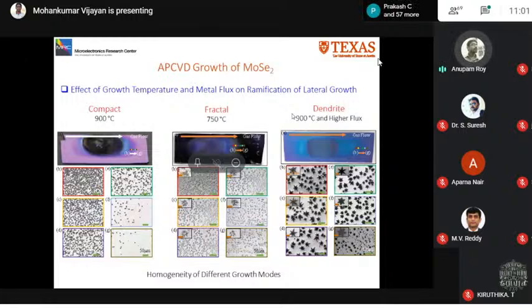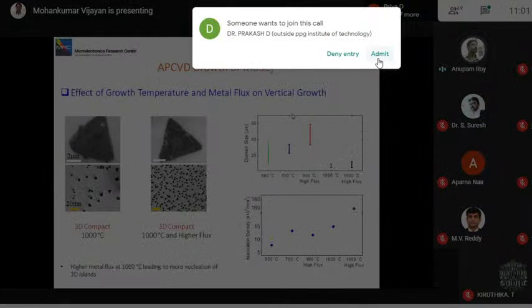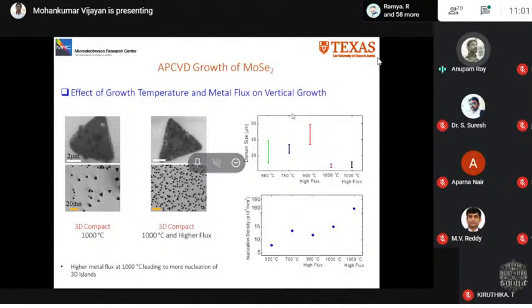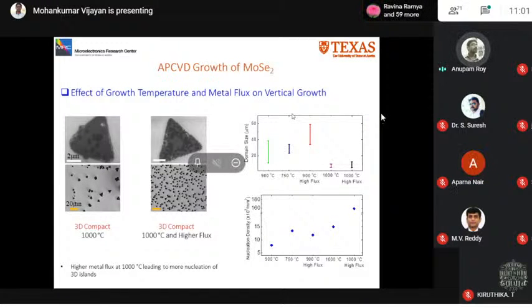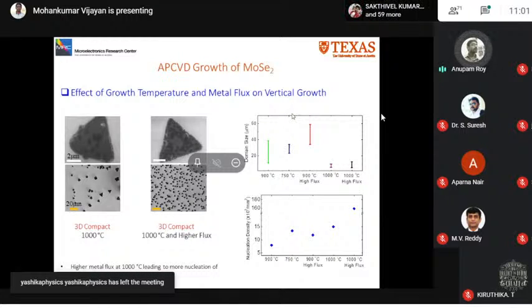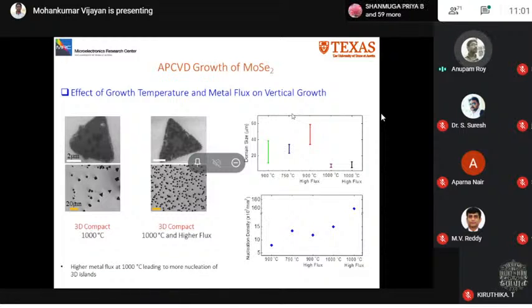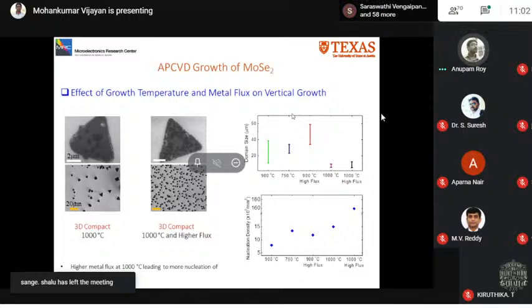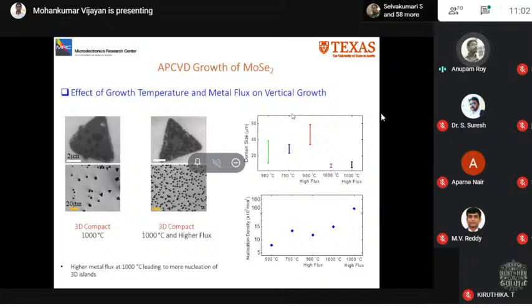In the next slide, I show that when the growth is conducted at a higher temperature, 1000 degrees C, we see that 3D island nucleation appears on a 2D domain, and the island nucleation is more when we have used the higher flux. That is probably because of twofold reasons. One is that at higher temperature we are increasing the metal flux also, and second is that at higher temperature selenium atoms will get dissolved faster, and that can create a selenium deficient condition. And why this selenium deficient condition, or the metal rich situation, is important, I will show in my next slide.